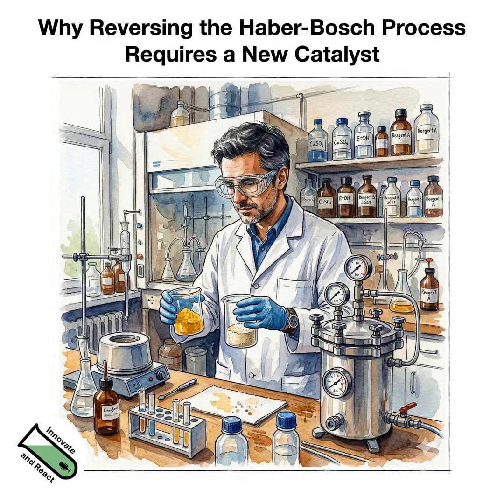And that is because when we decompose the hydroxide, we of course emit water from it. The water has to go somewhere. It leaves pores, it leaves void spaces that are all important in order to create those pores in the final catalyst that we want in the end. So those precursors are solid solutions of all components that we need, meaning that they are statistically distributed well, and the porosity is developed in a, maybe top-down, subsequent step from those precursor particles.